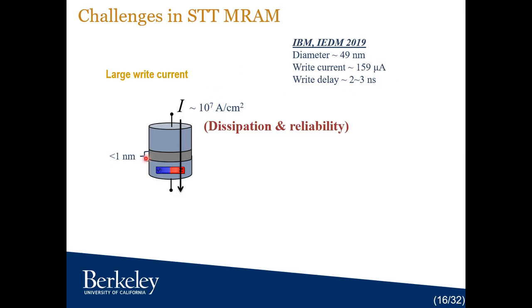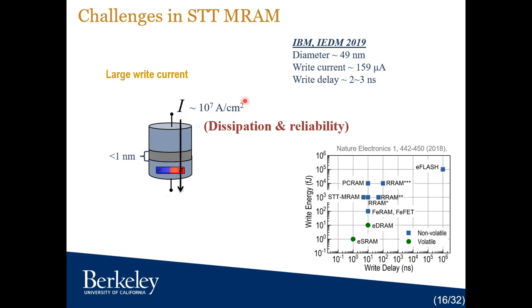Specifically, it creates some reliability issues because, as you remember, we have an oxide in between, and that oxide is very small, thinner than 1 nanometer, and it creates reliability issues in terms of breakdown. Other than that, large current creates dissipation because this is a resistive element, so I squared R is large, and that translates into large write energy.